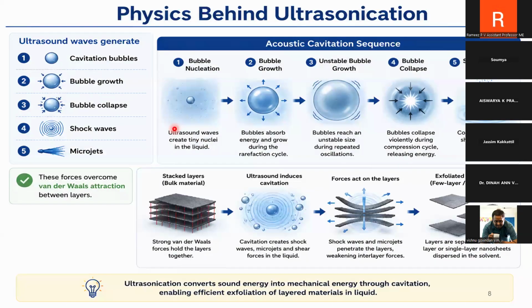And these bubbles have a tendency to grow, right? Because inside there will be air, and this will grow, and at a point it will burst out. So these things happen after intercalation. The intercalation is nothing but, see, these were the stacked layers. So once I put this bulk material into the solvent, the solvent will get into these stacked layers, and the bubbles also do the same. And this bubble will grow and sputter, or the so-called bubble collapse happens between these layers. And that sudden collapse is called cavitation.